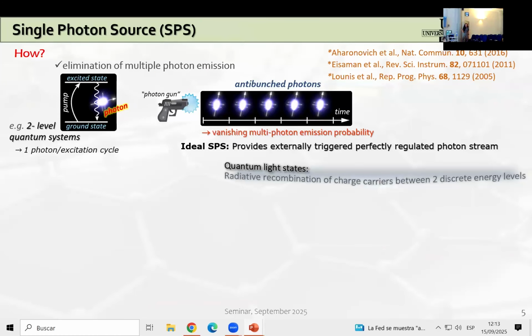Now, let's see how we actually generate single photons using solid state systems. For that, we need to have a radiative recombination of charge carriers between two distinct, discrete quantum levels. So what we need actually is a two-level quantum mechanical system consisting of a ground state and an excited state. This system emits only one photon each time it is excited. As a result, we get these anti-bunched photons as seen here. This means that the probability of having multiple photon emission per excitation cycle is practically eliminated.